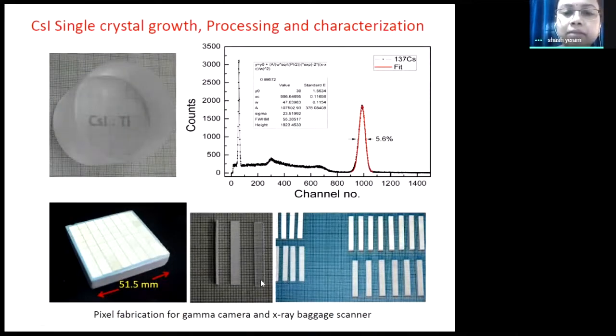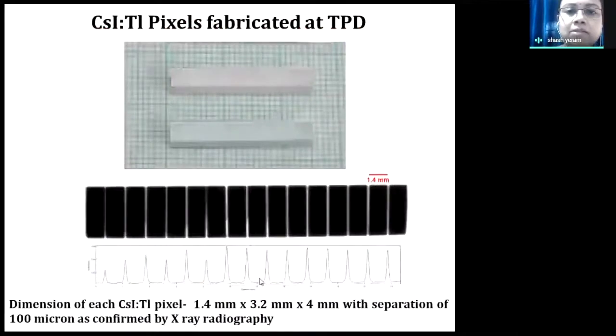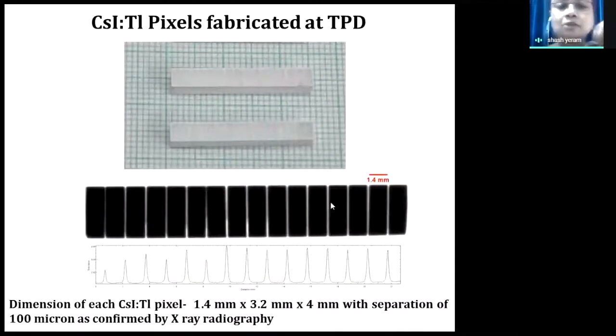So this is a 2D matrix, and this is 1D. In this photograph you can see there are 16 pixels. These are used when we have to do the imaging. This is the radiography image of these 16, to show how uniformly they are stacked together. Each pixel of cesium iodide has a width of 1.4 mm and a length of 3.2 mm, and the separation between them is 100 micron.